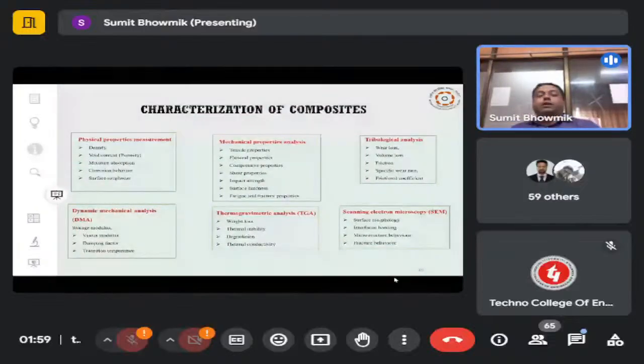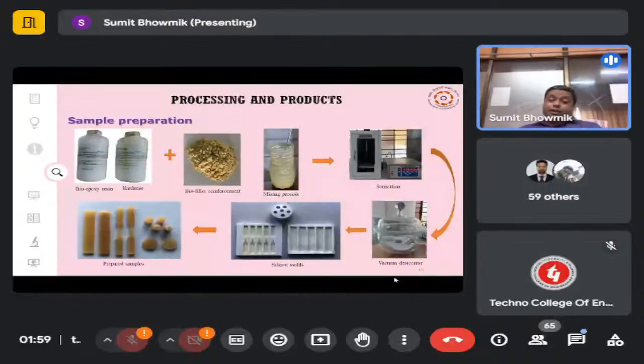Now, one more thing I have to mention: to make the sample or the product, there is some work that needs to be carried out in between. Whenever the filler has been prepared, it needs to go through some chemical treatment, because in most cases we have collected the raw fiber or filler from the open environment, so it contains a large amount of moisture, foreign dust particles, and other foreign particles which need to be cleaned up for making proper bonding between the resin and the hardener of the component. So the chemical treatment before mixing with the hardener or bioepoxy resin has to be carried out.